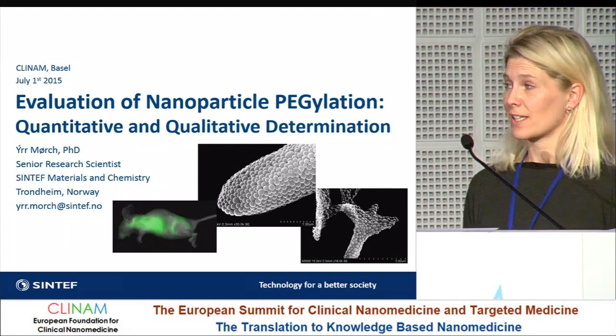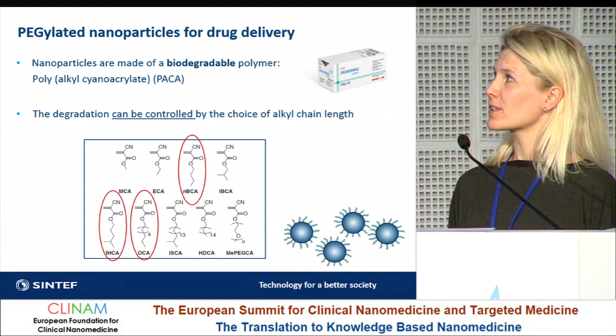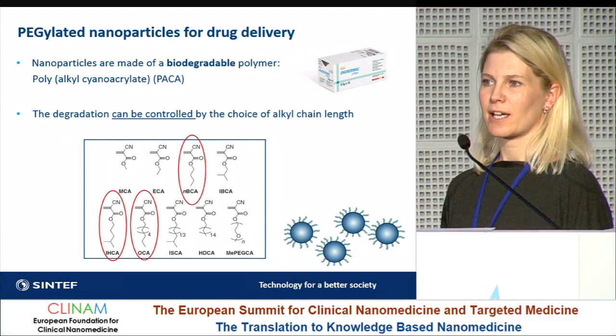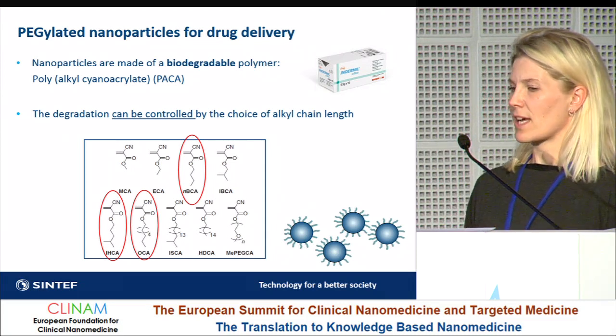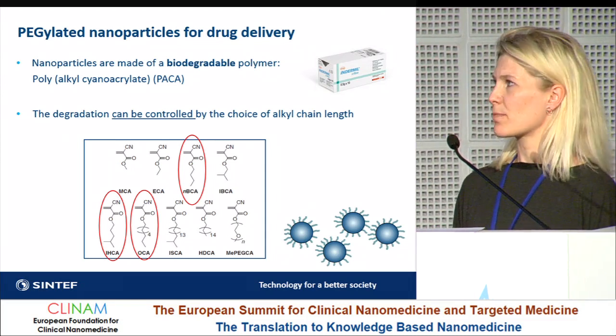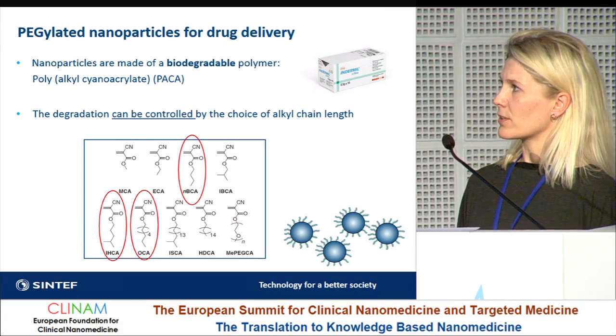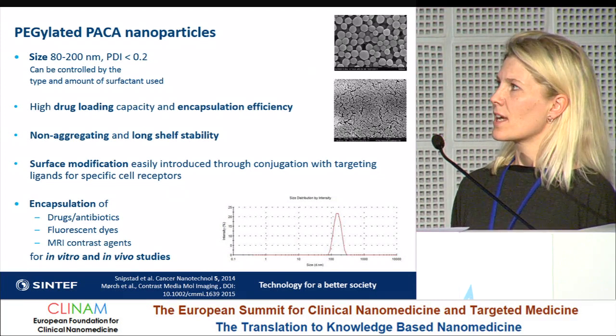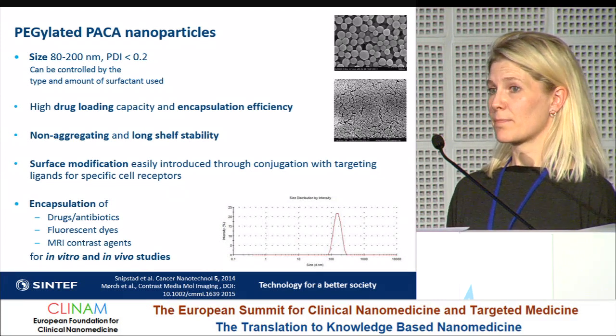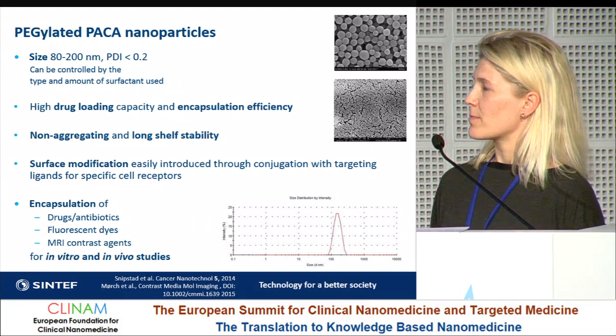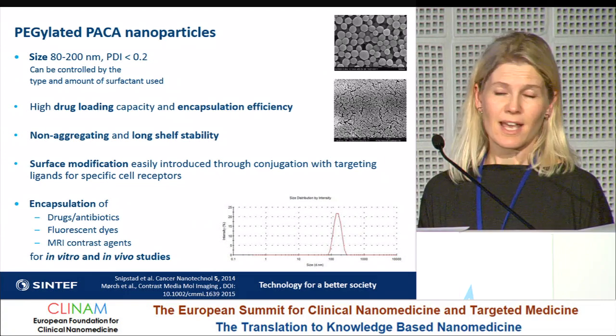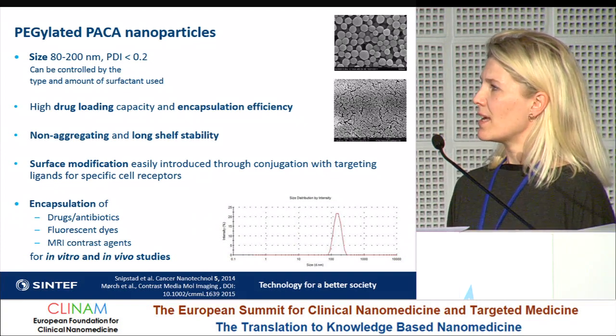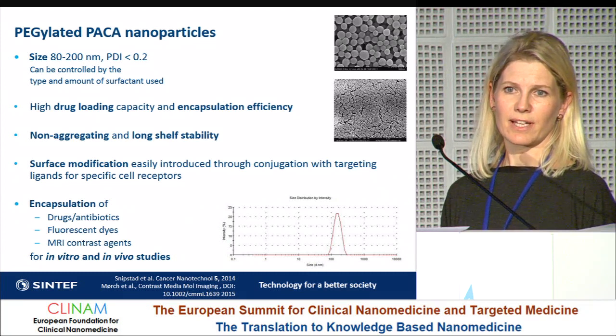We are working on PEGylated nanoparticles for drug delivery. These nanoparticles are made of biodegradable polymer polyalkyl cyanoacrylate, the same material used as medical adhesive in surgery, so it is biocompatible. We can control the degradation, and the particles can be made in sizes from approximately 80 to 200 nanometers by controlling the type and amount of surfactant. We make these particles by miniemulsion polymerization, allowing very high drug loading capacity and high encapsulation efficiency.